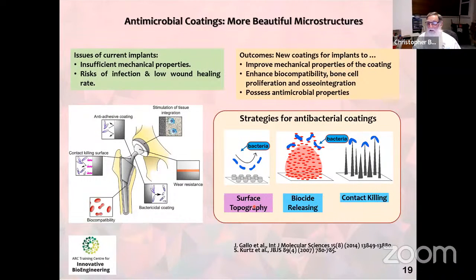How do we design the spray? How do we design the control, the temperature, the velocity, the particle size distribution, so that the surface roughness repels bacteria? How do we control surface roughness? How do we control the standoff distance and the thermal spray parameters so that we have porosity, so that we can have a biocide penetrating in 3 dimensions throughout the thickness of the coating?